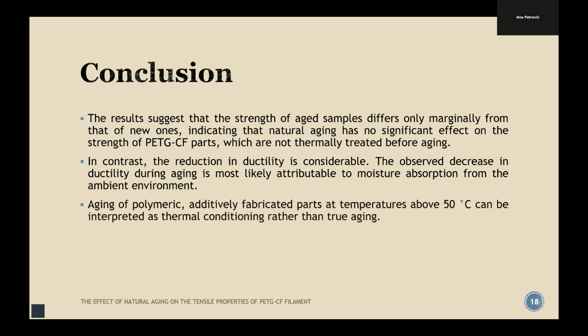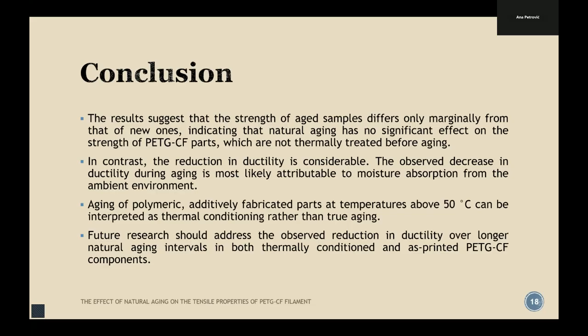Aging of polymer additively fabricated parts at temperatures above 50 degrees Celsius can be interpreted as thermal conditioning rather than true aging. Further research should address the observed reduction in ductility over longer natural aging intervals in both thermally conditioned and as-printed PETG-CF components. So we can compare them and see if there's a difference.